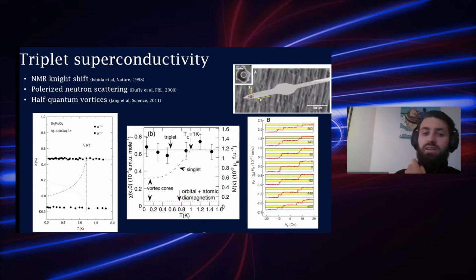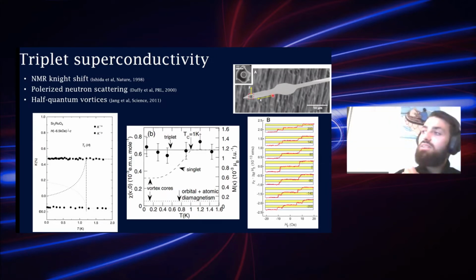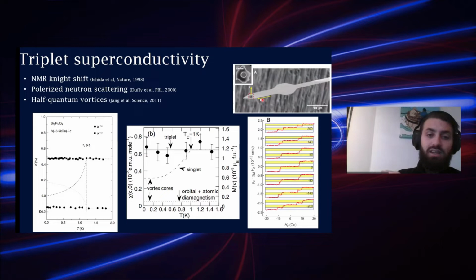This was found by cantilever magnetometry, where the half quantum vortices are stabilized by introducing an in-plane magnetic field to very small rings of strontium ruthenate. And interestingly, these fields are around 20 millitesla in plane.